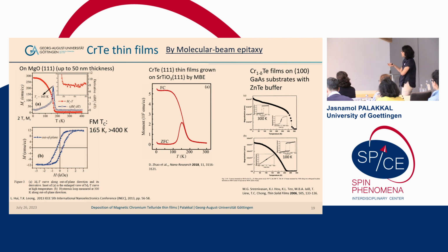And in another report, they even observed the TC above the room temperature, but in this case, when they measured the magnetic moment in plane in two different directions, they got different hysteresis loops. So this is a problem when you grow thin film. If you are getting magnetic properties or any physical properties inhomogeneously, then first of all you have to check if the structure is homogeneous or not. If you are growing a homogeneous thin film and you are getting anisotropy in plane, then this means that either it's really originating from the structure or the film was grown with a gradient, either in stoichiometry or in the crystal structure.